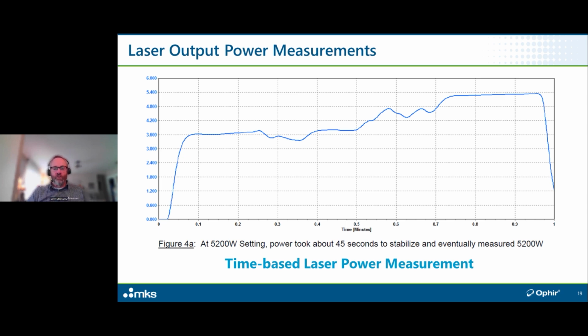I like to show this graph because it really is a good illustration of why I think it's important to take time-based measurements. This was on an older CO2 laser, and this particular customer had a very inconsistent cut with their sheet metal, and they called us in to troubleshoot. You can see that at the 5.2 kilowatt setting, the laser started off stabilizing at roughly 3.6 kilowatts or so. It was bouncing around for several seconds, and then ultimately around 45, 50 seconds or so, it stabilized at that 5.2 kilowatts. Well, if you are using this laser for cutting, you're making these long cuts, you can visualize what's happening to the cut, right? You're starting off with a very, very unstable cut. You don't really know what's going on, and then it's finally stabilizing towards the end of the cut.